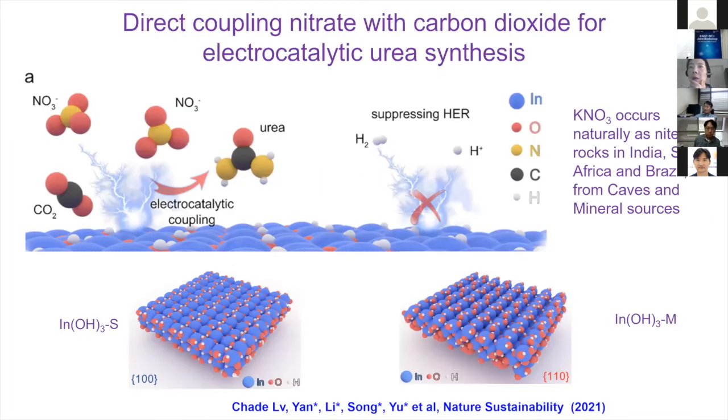So in this process, this work we work with Professor Yu Guihua and Professor Song Li and Professor Li Shuzhou. Shuzhou gave a presentation yesterday together. So we try to show that on the surface of indium hydroxide, there's a proper coordination, actually 4 active sites together can allow the proper anchoring of a nitrate and the carbon dioxide. And this will promote the bridge, or we call it linkage, between the nitrogen and the carbon to form a carbon nitrogen